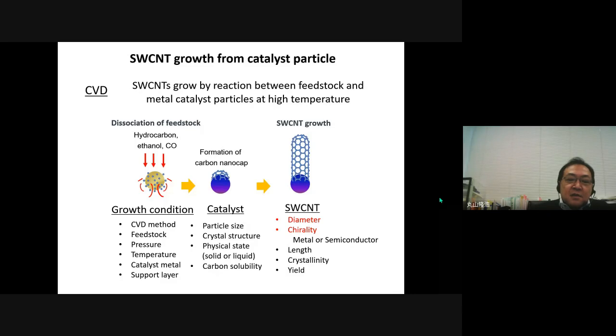So as I mentioned, in CVD, nano-sized metal catalysts react with feedstock gas at high temperature to grow carbon nanotubes. In this process, the physical and chemical states of catalyst particles are considered to affect the nanotube structure. The electronic states of single wall carbon nanotubes are determined by their structure, such as diameter and chirality. Therefore, understanding the state of catalyst particles is important to control the structure of an SWCNT.